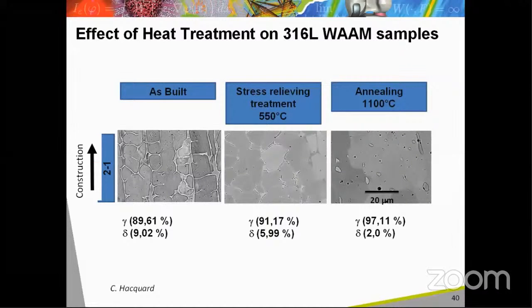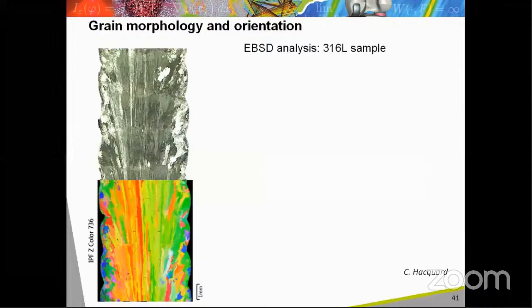Another specificity of the materials obtained with the WAAM process is a strongly oriented grain structure. This is because the solidification is highly directional, because the thermal gradient is oriented mainly in the build direction. Consequently, the grains have a columnar morphology, as we can see on the picture on the left side of this slide. In addition, the growth direction, for an FCC structure, is the 100 crystallographic direction.